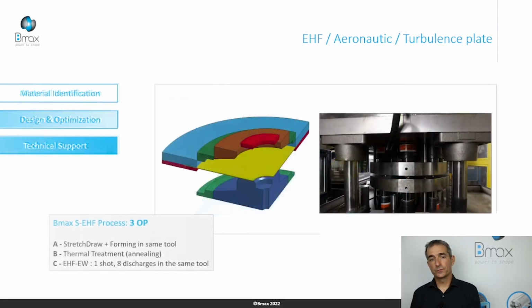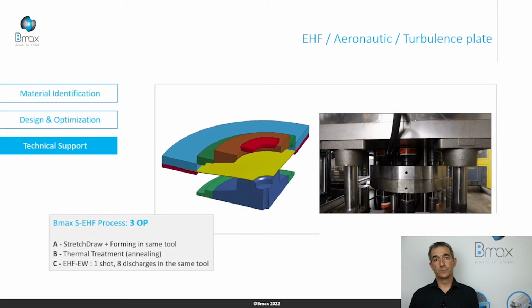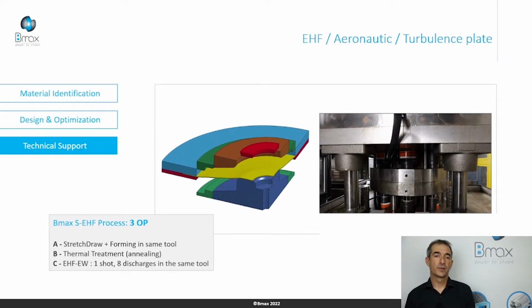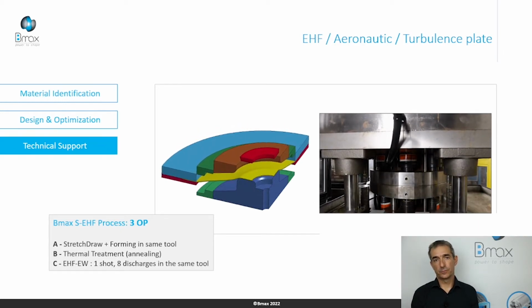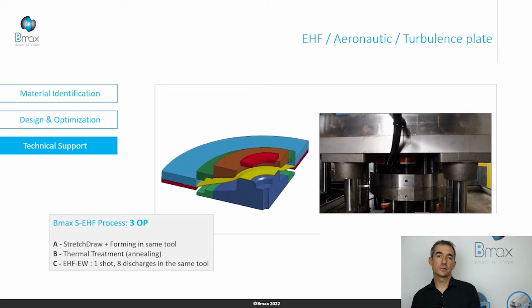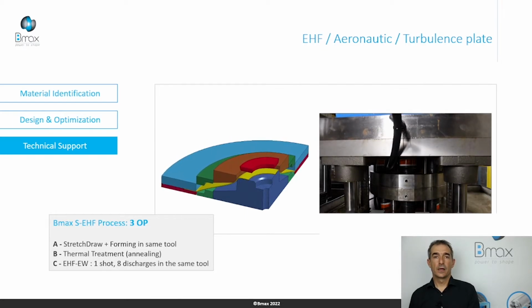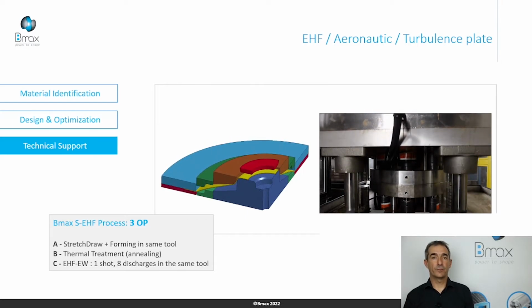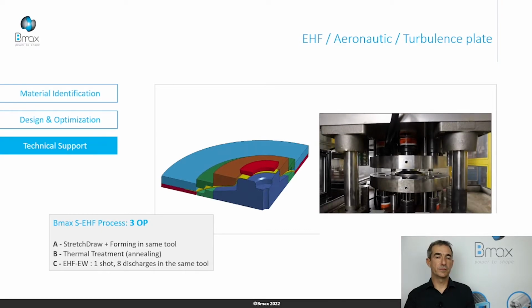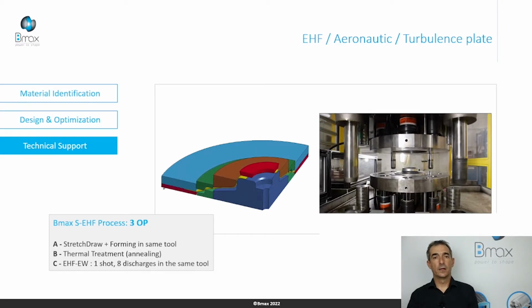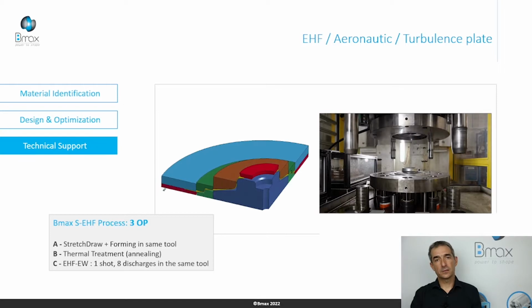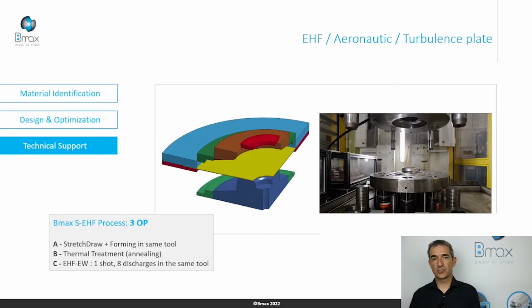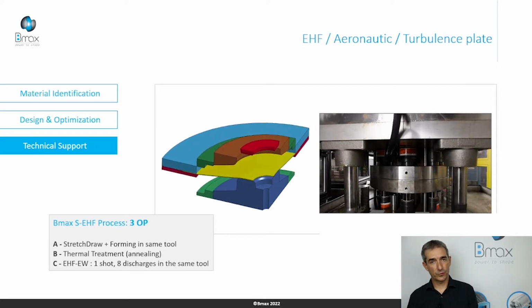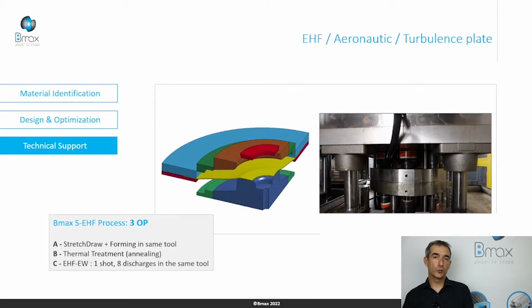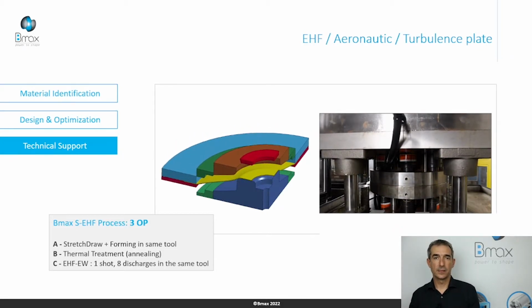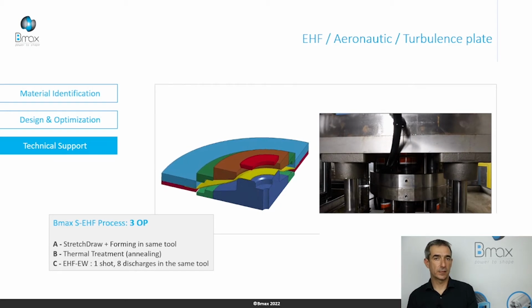In the real world, we proceed with this double-acting process, with the stretch draw combined with a stamping. As you can see on the left, we have a blank holder. The blank is clamped between the blue and the red part, and this area is not submitted to EHF calibration. That's why in the real world, we proceed to thermal treatment to relax the stress in this area and to avoid any defect from the springback.